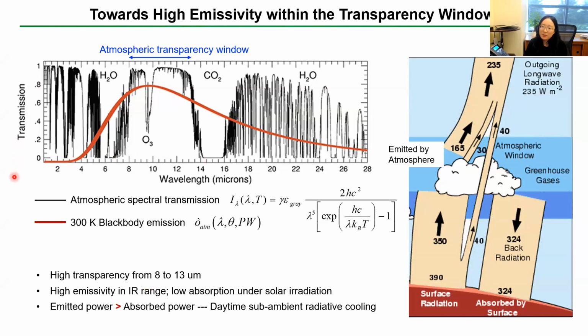When we look at the transmission spectrum, this is the transmission versus the wavelengths in the IR range. You would immediately notice that from 8 to 13 micron, the transmission is almost 1. We call this the atmospheric transparency window. When Earth is radiating as a 300 Kelvin black body, the radiation within 8 to 13 micron gets transmitted through. So in theory, anything that is strongly emitting within this range will be able to get cooling energy,